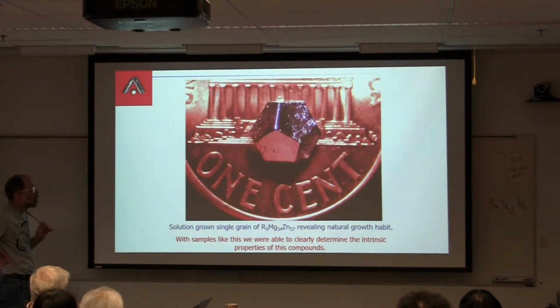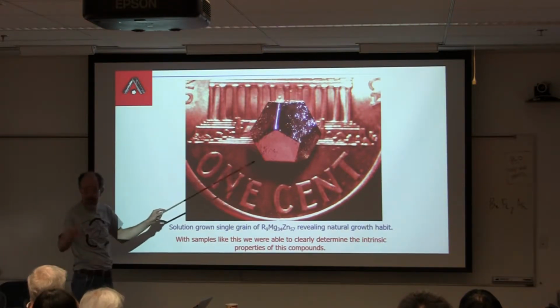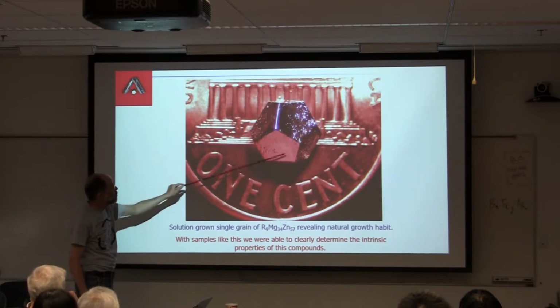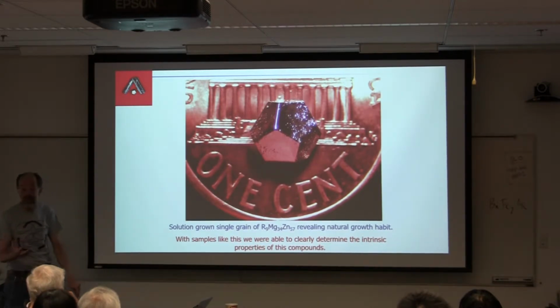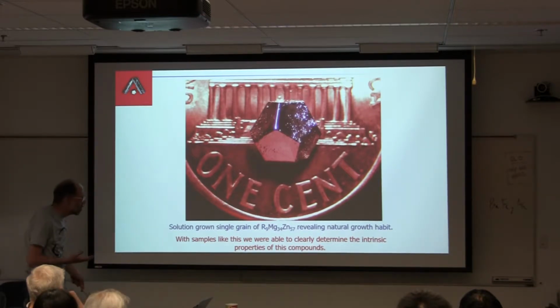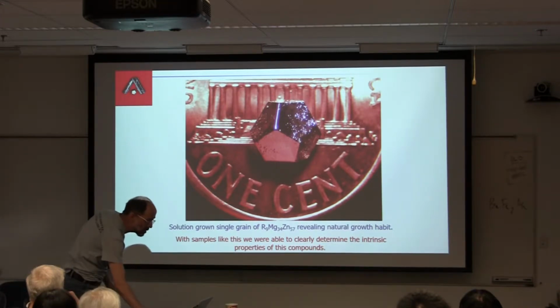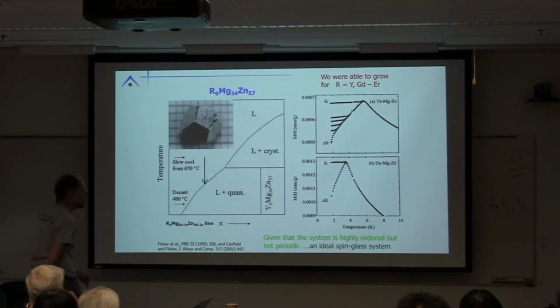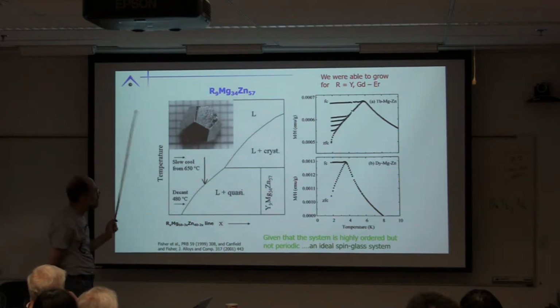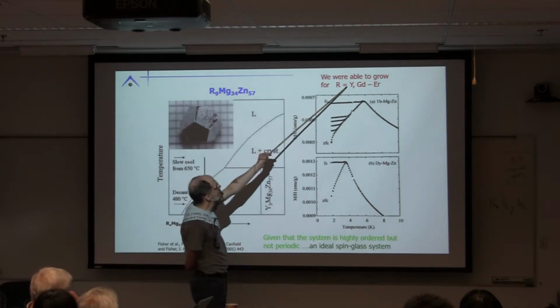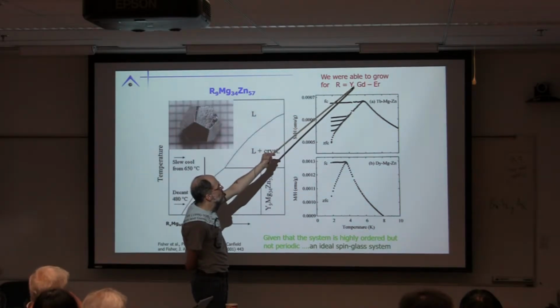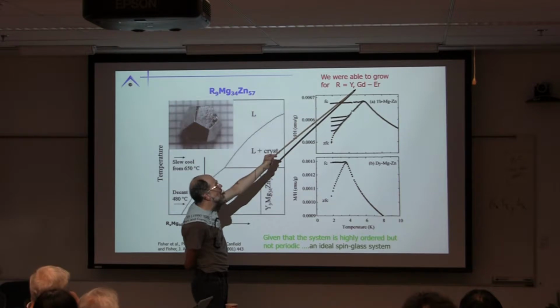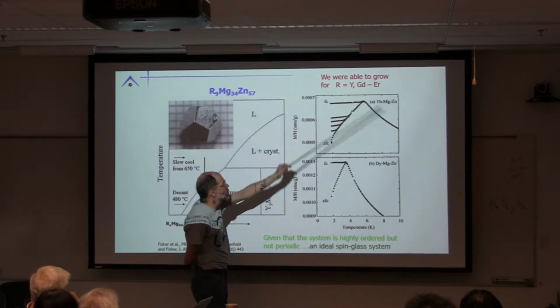Now, with that in hand, we were able to grow what ended up being the iconic pictures of quasicrystals. You can count, Lauren, you can count with me, 1, 2, 3, 4, 5. These are 5-sided facets. This is a forbidden, historically crystallographic symmetry. Okay? So A, it was pretty and nice, but B, what it allowed us to do then is to look at materials that had highly ordered but not periodic rare earth sublattices. Okay? We could grow it for the non-magnetic yttrium, but we could also grow it for the non-CEF split gadolinium and the CEF split terbium through erbium.